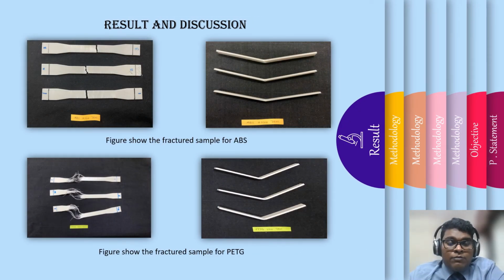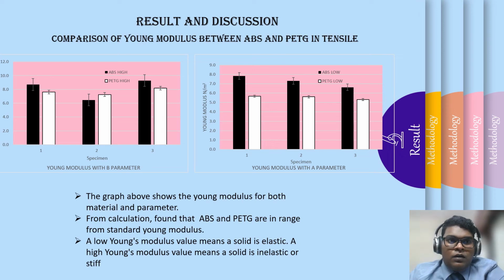Next, the image above shows the tensile and flexural specimens after conducting the performance test. For performance, first and foremost, the comparison of Young's modulus is a must. This is because the modulus can be used to identify whether the solid is elastic or inelastic. The graph above shows the Young's modulus for both materials, ABS and PETG, and both parameters, high level and low level, in tensile. From the calculation, we found out that ABS and PETG are in the range of standard Young's modulus.